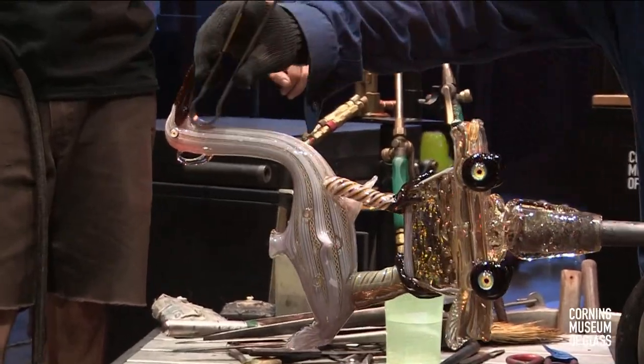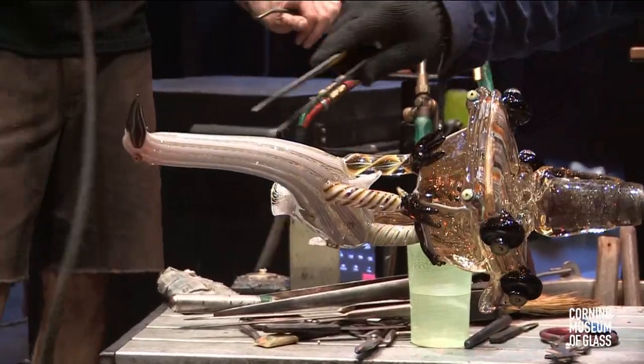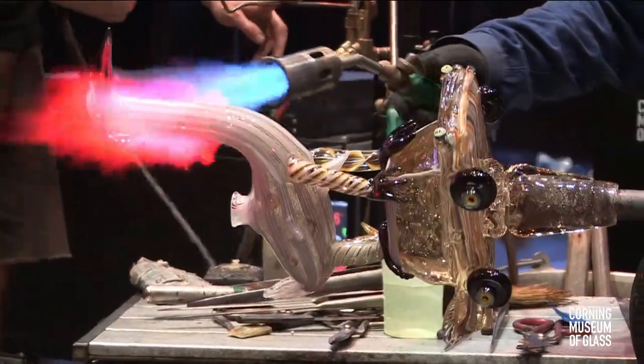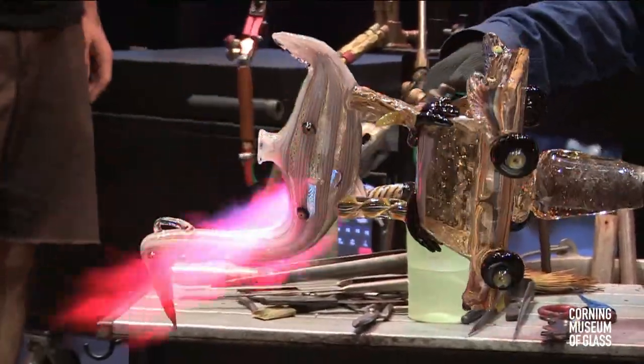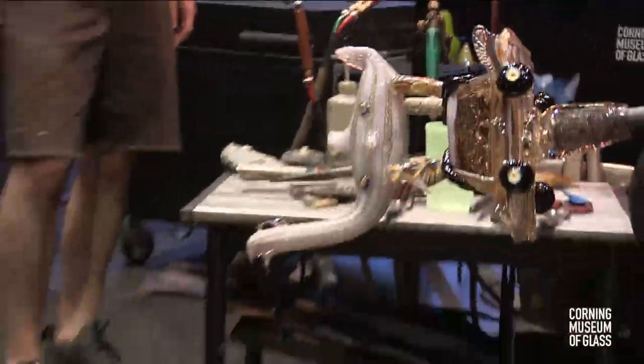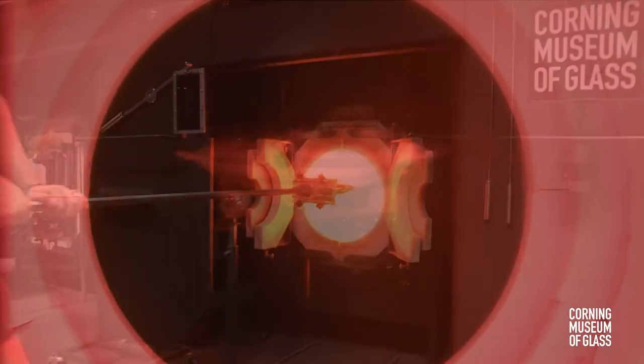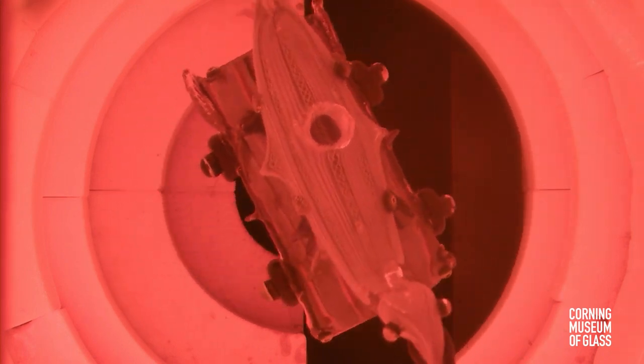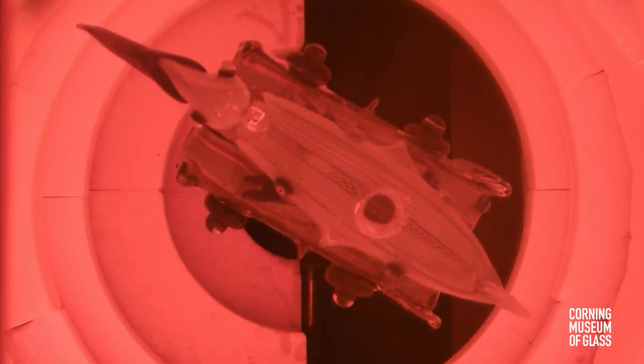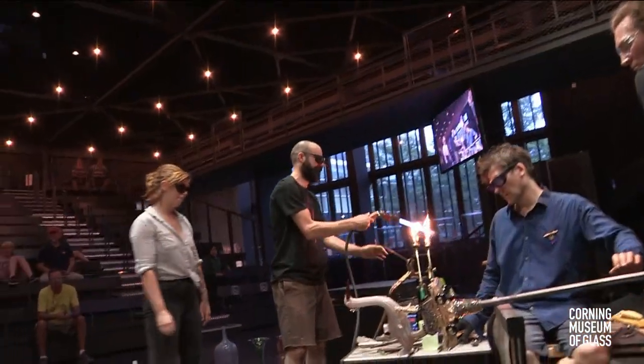And when you're working with the batch itself, it takes longer to get it to heat and melt and turn into glass and refine. It can take almost 24 hours to get a really nice glass to form out of that. And it takes higher temperatures and longer time. So it's a little bit more expensive to melt that glass from that raw material. But it also is a powder. And powders, silica in particular, can be hazardous to your health. So you need to make sure you protect yourself with proper PPE and everything. So we end up getting that pre-melted glass also for safety. So it makes it a lot easier for us to use.